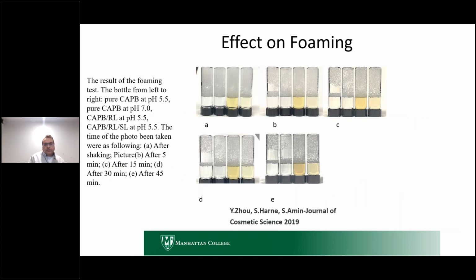So you see the ones with a slightly yellowish tinge are the biosurfactant-based systems that we've optimized at those ratios. And you see again here that the longevity and the quality of the foam, especially the second from the right, is quite different from even the traditional synthetic surfactants. So actually, to that question, we can not only substitute bio-based ingredients, but we can design, through formulation optimization, systems which actually outperform our traditional surfactant-based systems. So that's the take-home message for this aspect of things.